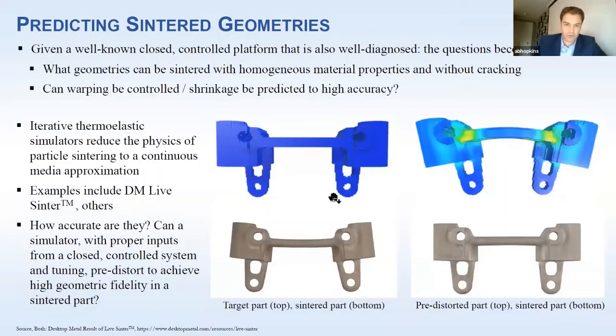Okay, but even in a controlled system, and I borrowed this from Desktop Metal's website, this is their Live Sinter, the thermoelastic model that pre-distorts a part. So here's the CAD on the top left. When you sinter it, you get this warp due to the sintering dynamics in a thermoelastic sense. So forget about particles. Let's pretend the particle problems are taken care of. You have a controlled repeatable system. Even then, you do have this warp that's introduced by the shrinkage.